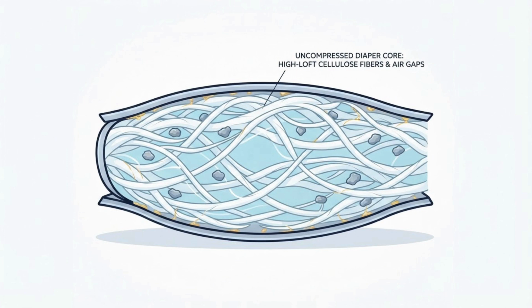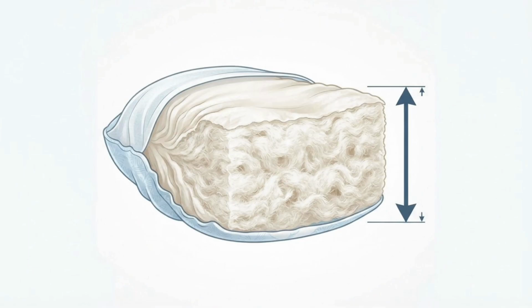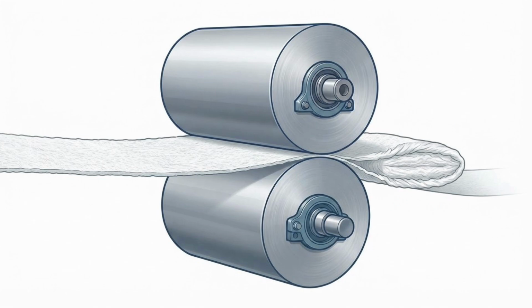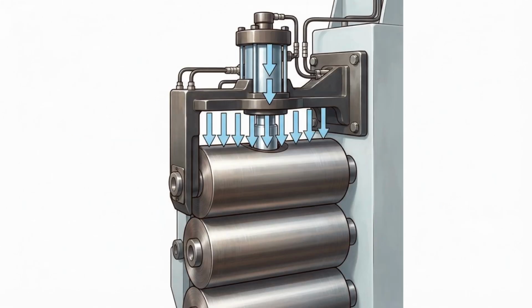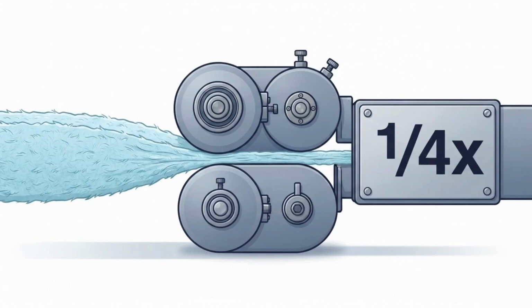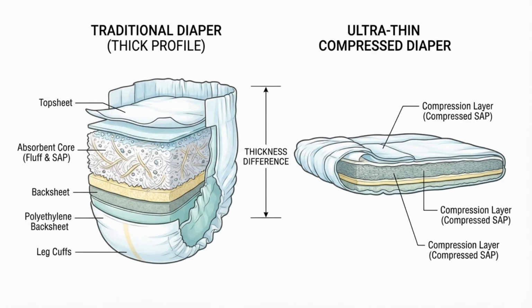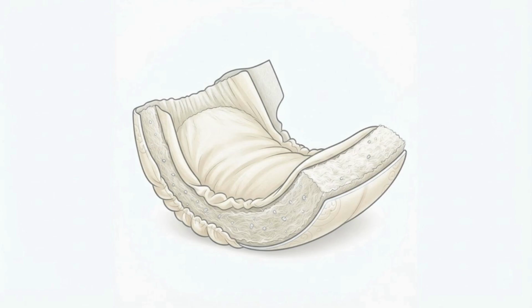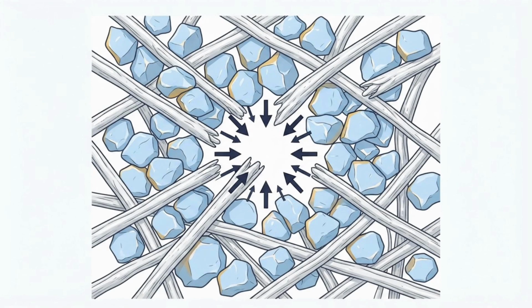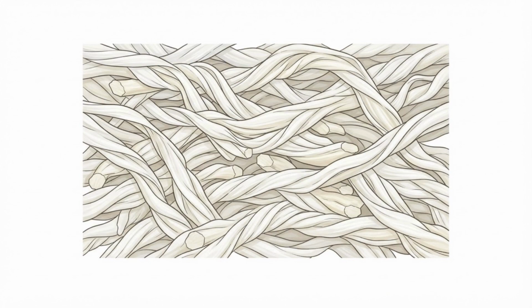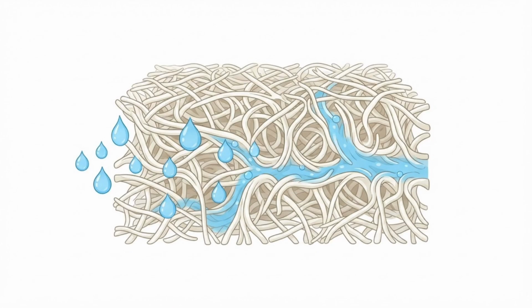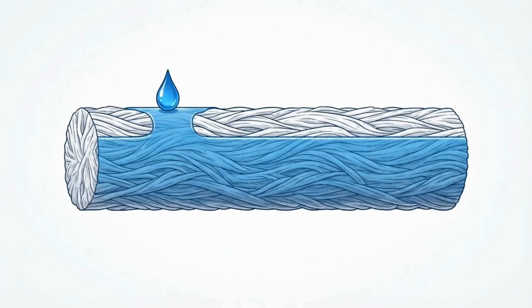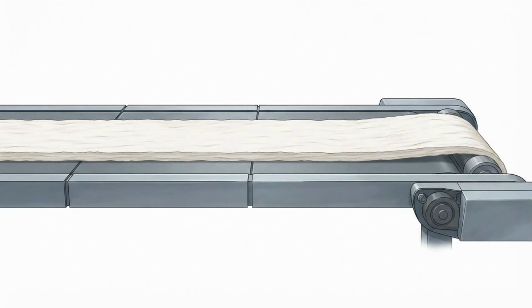At this stage, the core is highly aerated and far too thick. It passes through a series of heavy steel calender rolls that apply extreme hydraulic pressure, compressing the core to a fraction of its original thickness. This densification not only makes the final product thinner and more comfortable, but also decreases the distance between the microscopic cellulose fibers, significantly increasing the capillary action that gives the core its wicking power.